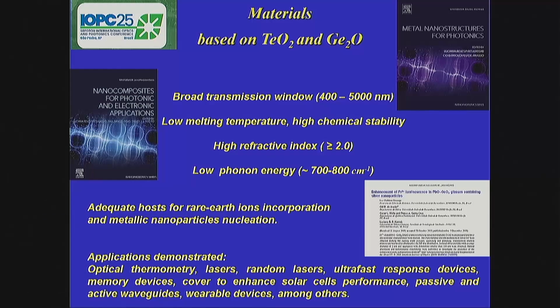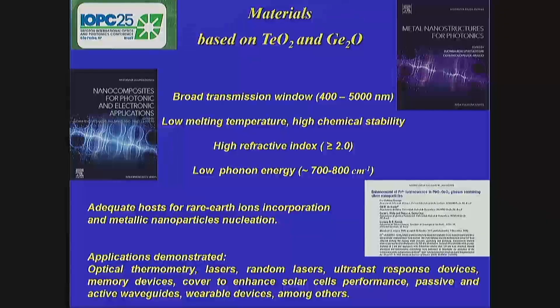These materials have some interesting characteristics. They have a broad transmission window from visible to near to mid-infrared region, around 5,000 nanometers, high chemical stability, low melting temperature with respect to silicates and borates, low phonon energy, which is important for the non-radiative losses, high linear and non-linear refractive index, which is also important for ultra-fast response devices, and they have demonstrated to be adequate hosts for the incorporation of metallic nanoparticles, and also for the incorporation of rare earth ions and for the nucleation of metallic nanoparticles.